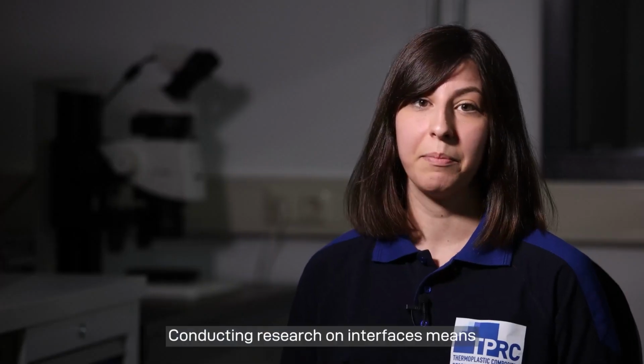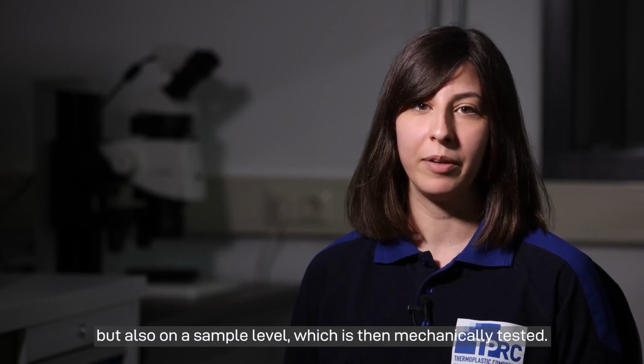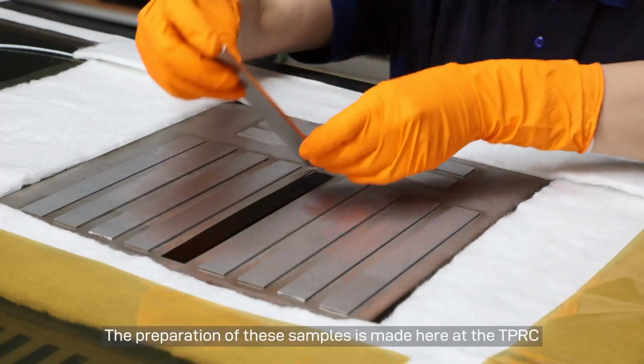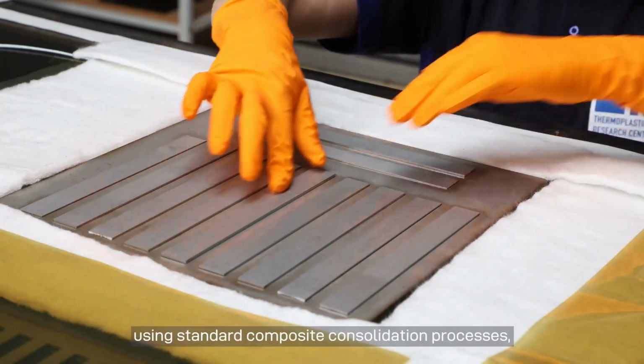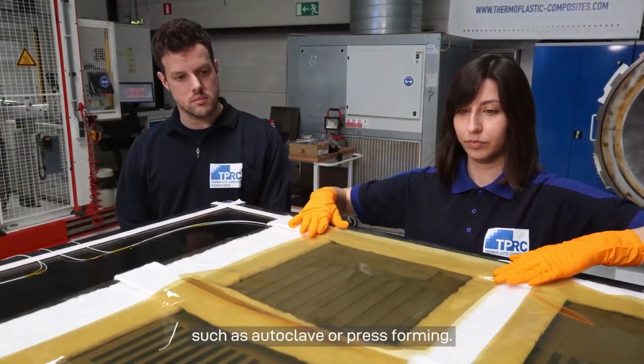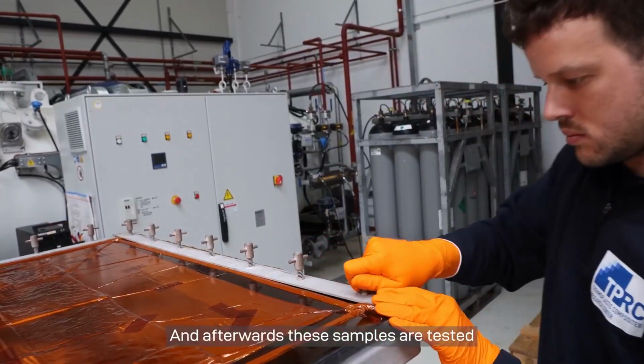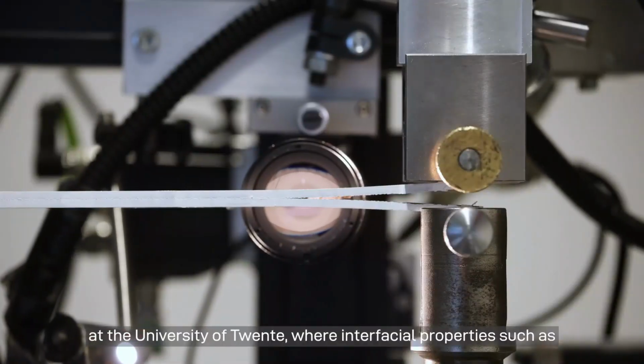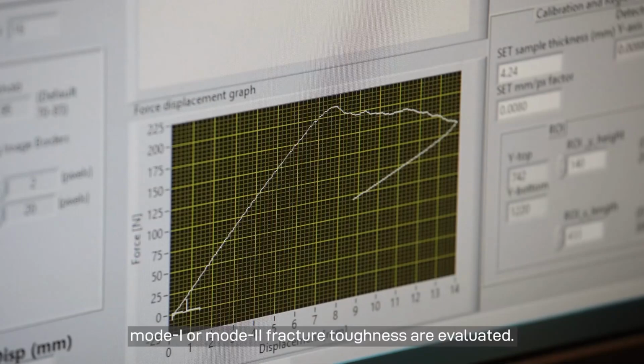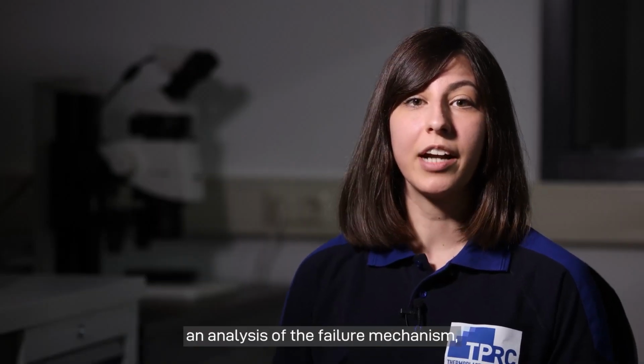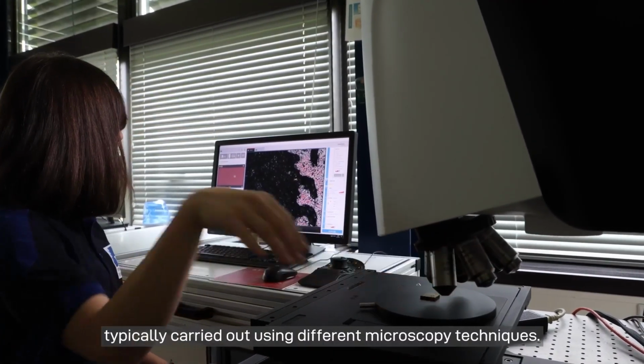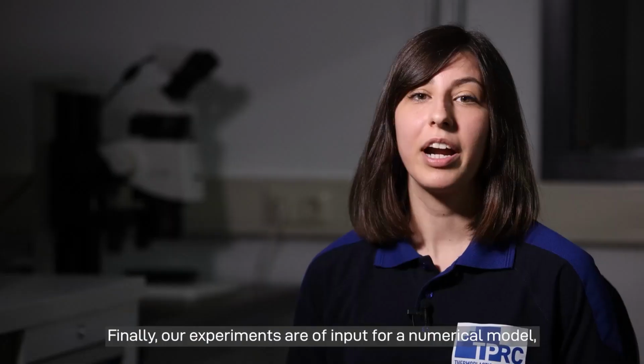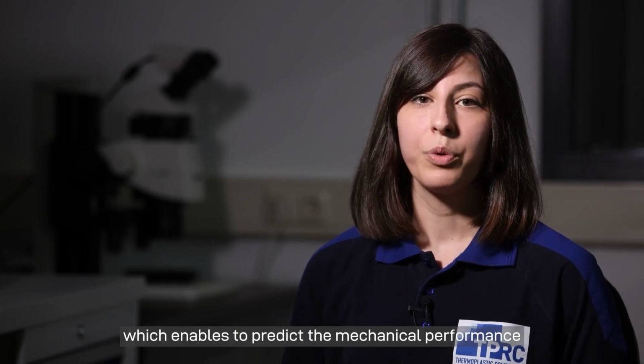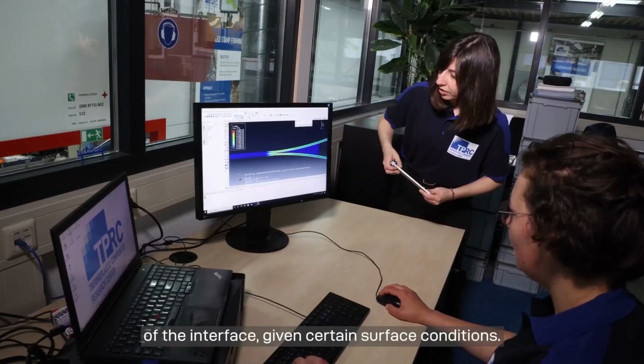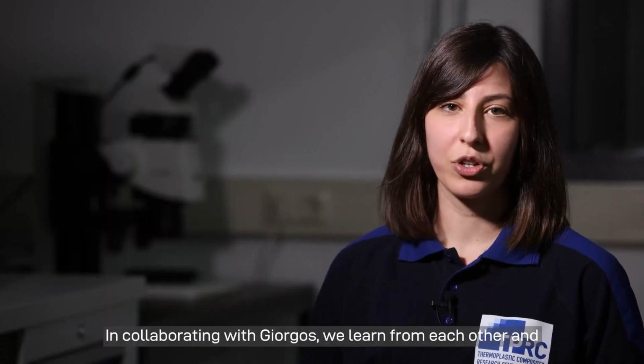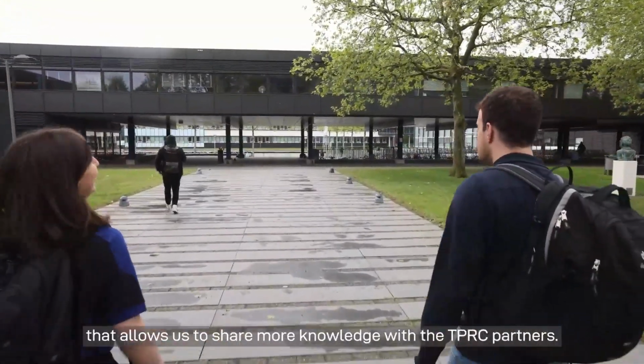Conducting research on interfaces means not just working on a part level, but also on a sample level, which is then mechanically tested. The preparation of these samples is made here at the TPRC using standard composite consolidation processes, such as autoclave or press forming. And afterwards, these samples are tested at the University of Twente, where interfacial properties such as Mode 1 or Mode 2 fracture toughness are evaluated. Mechanical testing is always followed by an analysis of the failure mechanism, which is typically carried out using different microscopy techniques. Finally, our experiments are input for a numerical model, which enables us to predict the mechanical performance of the interface given certain surface conditions. In collaborating with Yorgos, we learn from each other, and that allows us to share more knowledge with the TPRC partners.